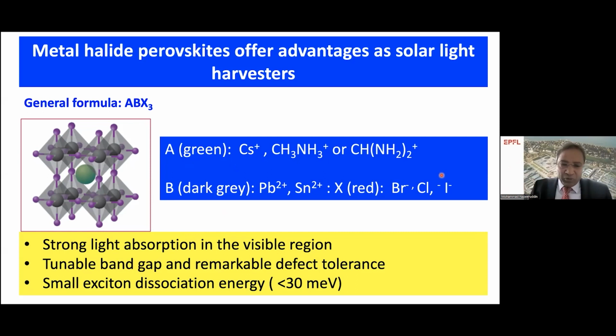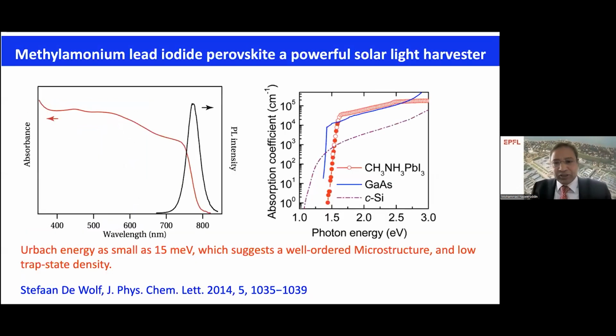The other interesting property of these materials is a small exciton dissociation energy. When you shine light on these materials, they create charges, and the dissociation energy is so small that the charges are diffused to the contacts. These are very interesting properties of these materials. As I mentioned, the absorption spectral properties are shown on the left side of the viewgraph. The onset starts around 800 nanometers and goes down to 400 nanometers, so it absorbs the whole visible region of our solar spectrum. And wherever you excite, you will have a very nice emission coming around 820 nanometers.